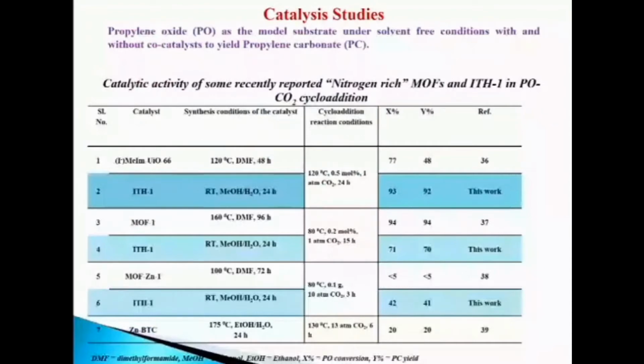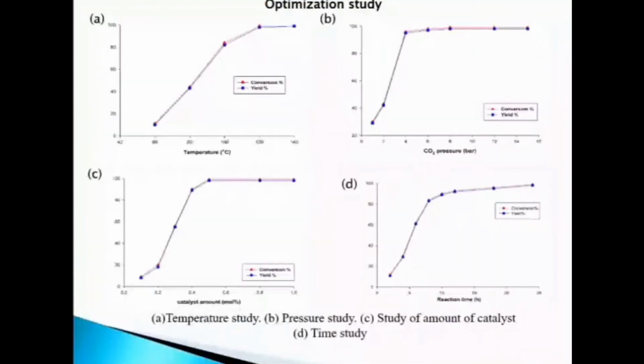Here, using propylene oxide as substrate, we are carrying out the catalysis with and without co-catalyst to yield propylene carbonate. With our catalyst ITH1, it renders 93% conversion of propylene oxide with excellent selectivity towards propylene carbonate. We also carried out the reaction with precursor materials of ITH1, which shows only negligible conversion, as observed in this table. From this, we can understand that at 120 degrees Celsius, 93% conversion occurred, and at 6 bar pressure, 94% propylene oxide conversion occurred and was retained. 24 hours and 0.5 mole percentage of catalyst was found most suitable for efficient transformation.